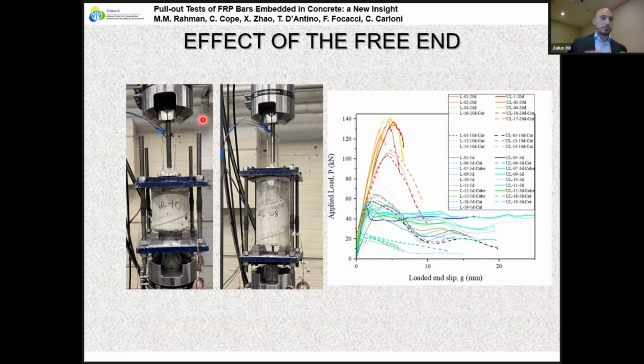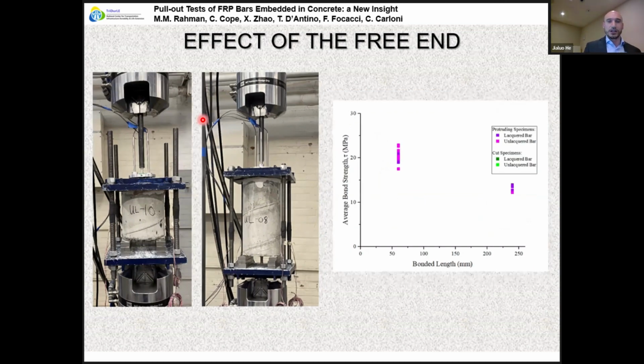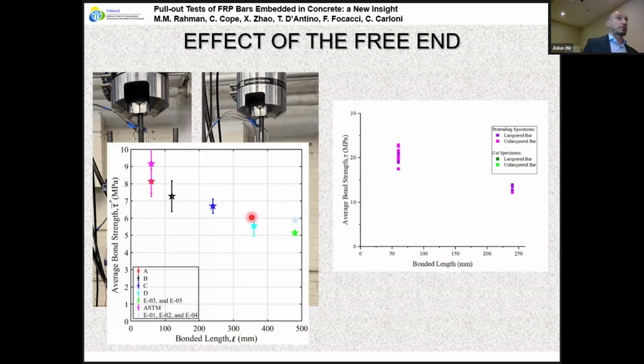This one is a ribbed bar, the same specimen, all the lengths, the cubes. Actually, the manufacturer had two different bars with a different coating. So we cast a lot of specimens, and we tried to see if there was a difference. What you see here is the tau, the peak load normalized by the area of the bond, versus the bonded length. And just to compare, these are the results of the previous bar, the same coated. So we said, okay, it seems like this is the same result.